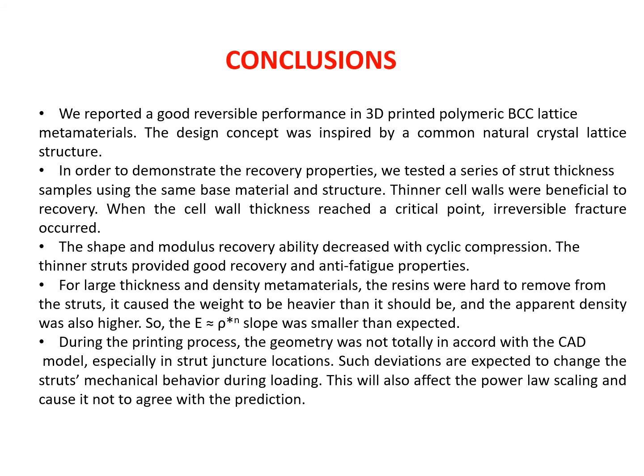For large thickness and density metamaterials, the resins were hard to remove from the struts, which caused the weight to be heavier than it should be, and apparently the density was also higher. So the E versus rho star to the n slope was smaller than expected. During the printing process, the geometry was not totally in accord with the CAD model, especially in strut juncture locations. Such deviations are expected to change the struts' mechanical behavior during loading. This will also affect the power law scaling and cause it not to agree with the prediction.